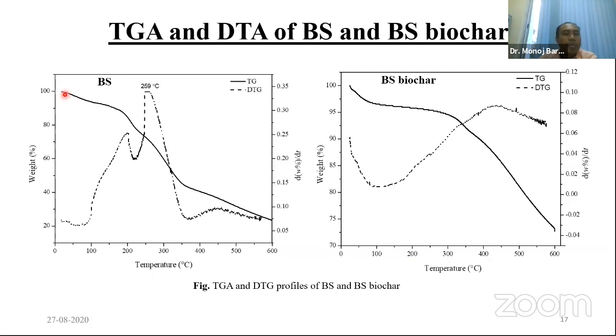We can see that the mass has decomposed and come down from 100% to around 25%. So we can see that 75% of the biomass has degraded. This line shows the degradation of the mass of the biomass. From that we can understand that within a temperature range of 600 degrees Celsius, we can get 75% decomposition of the biomass. And from the DTG profile, at around 250 or 259 degrees Celsius, the highest rate of degradation is found. As I said, the DTG profile gives the information on the rate of decomposition, that is dW/dt.